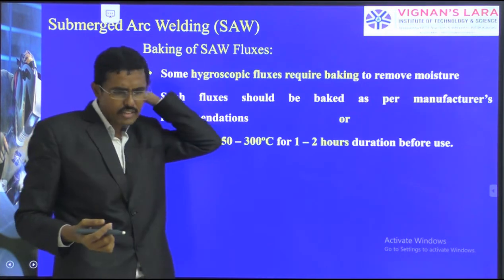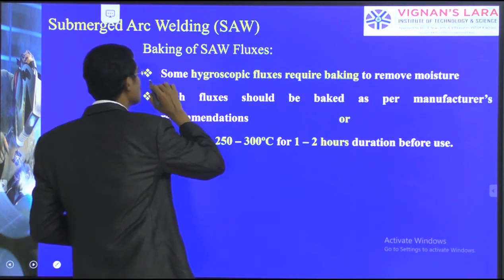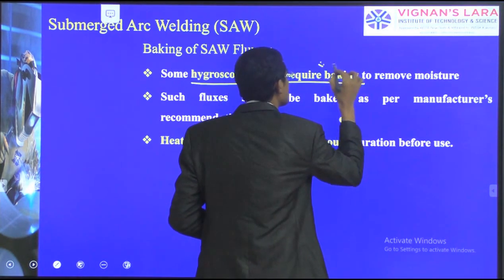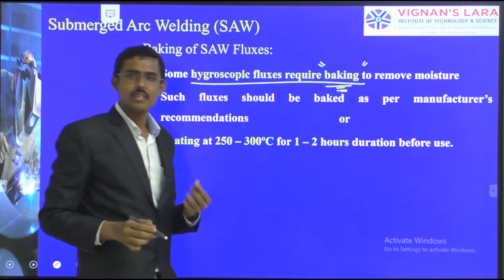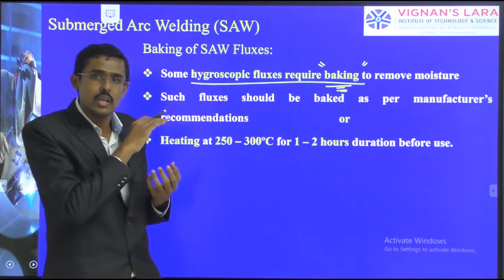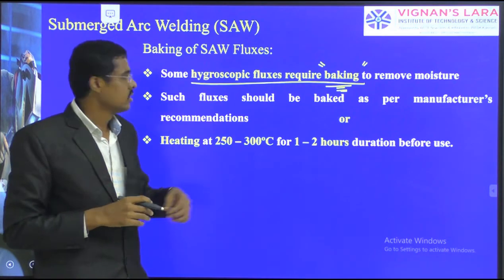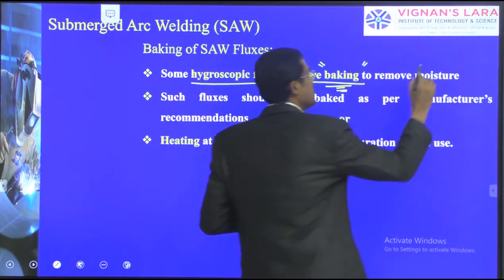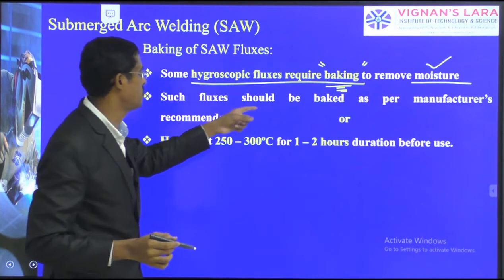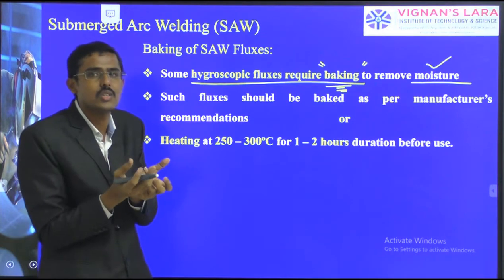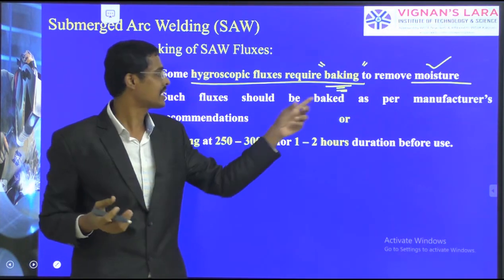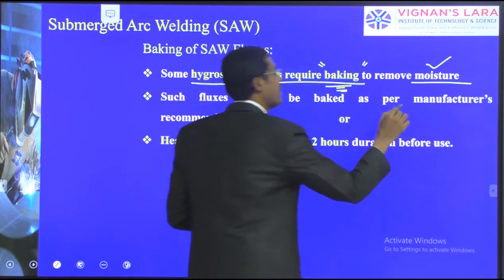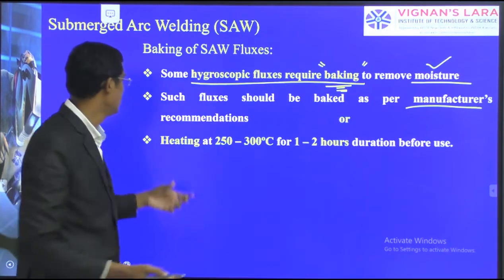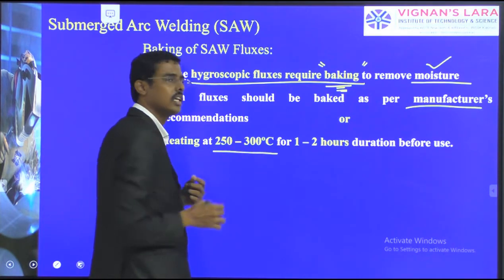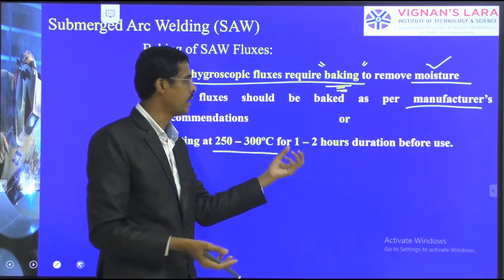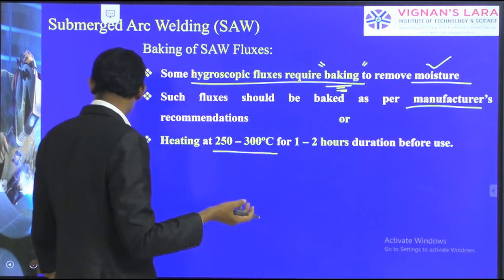So you can see the baking of the SAW process, how we should do it. Some hygroscopic fluxes require a baking process. See, because of the hygroscopic absorbing tendency, moisture should be removed first. Therefore, it should be baked to remove the moisture. Such fluxes should be baked as per the manufacturer. How much temperature it should be baked at before use in industry? The supplier manufacturer will give the manual, or otherwise in general they say heat up to 300 degrees centigrade for 1 to 2 hours in the oven, and we can then use it. So that methodology we can follow.